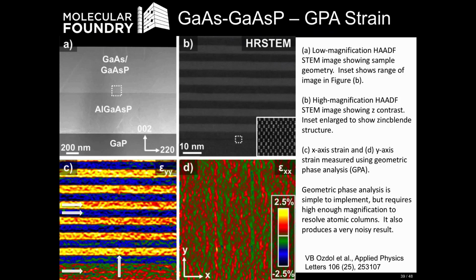So if we zoom in on that, we can use conventional high resolution STEM imaging to form an atomic resolution image. That's what I'm showing in panel B here. The white box is a zoomed in image showing the dumbbell structure that we can see. And by measuring the shift of these peaks, we can form a strain map, which I'm showing on the lower left and the lower right here in panels C and D.